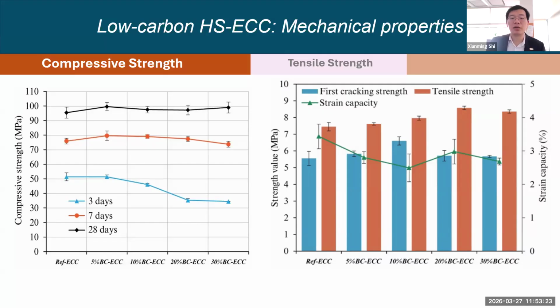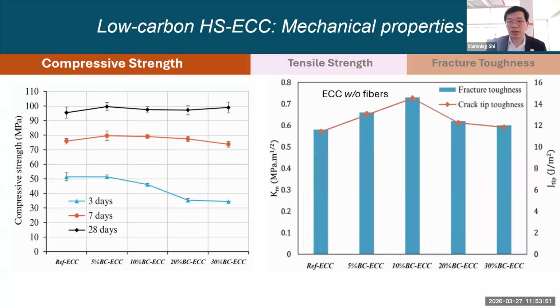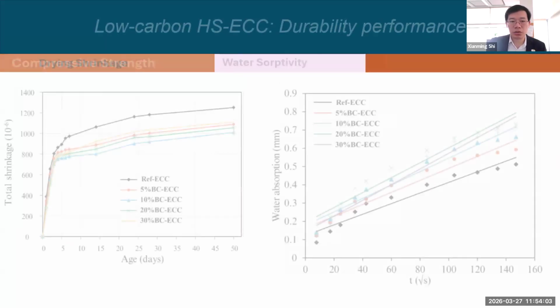Okay, the first cracking strength sort of peaked at 10%, but even at 30%, you're still comparable with the control. The strain capacity did decrease compared with the control, but again, even that is still above 2.5%. So that's sufficient in most applications. So fracture toughness again peaked around 10% replacement of cement by biochar, but even at 30%, it's very similar or slightly better than the reference. So it's all good news.